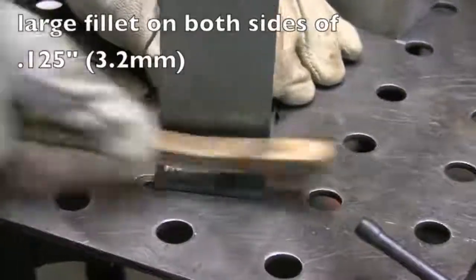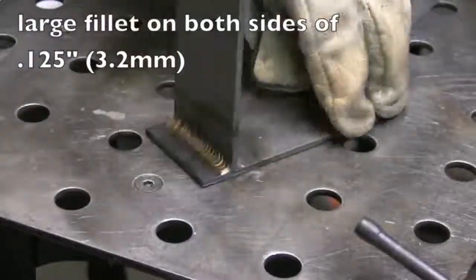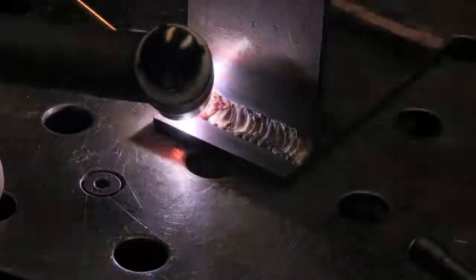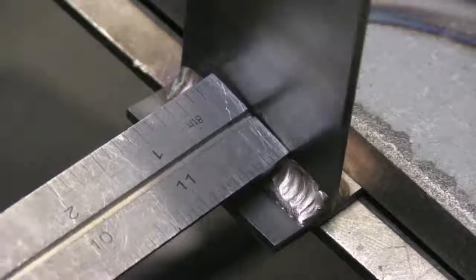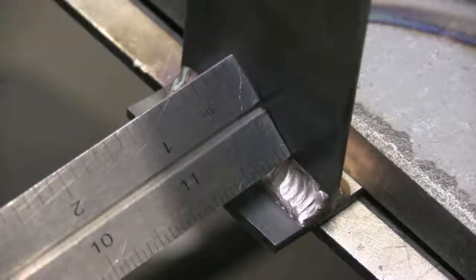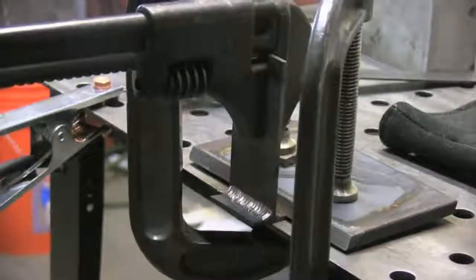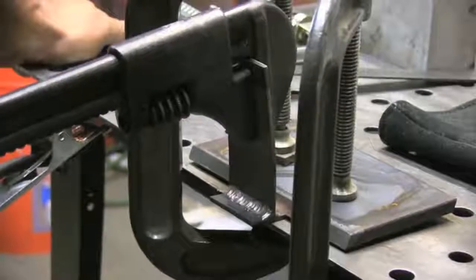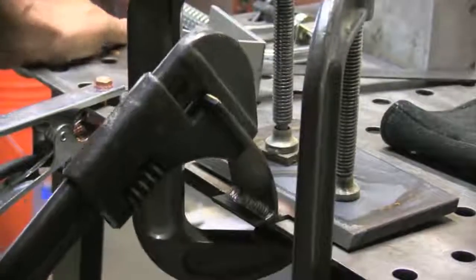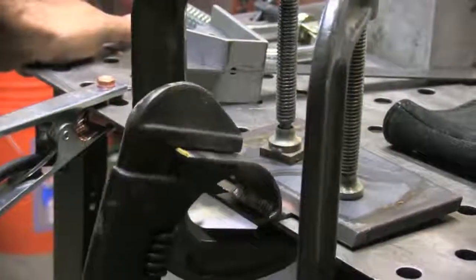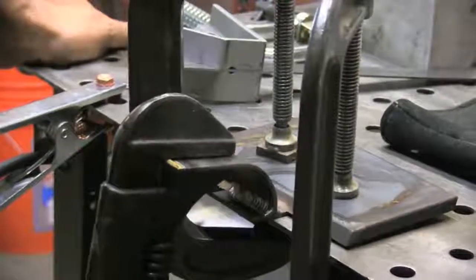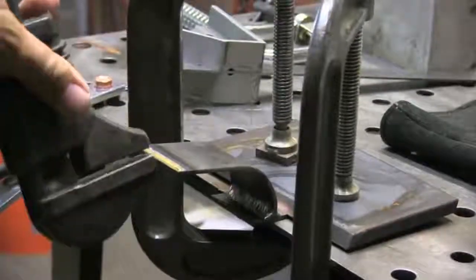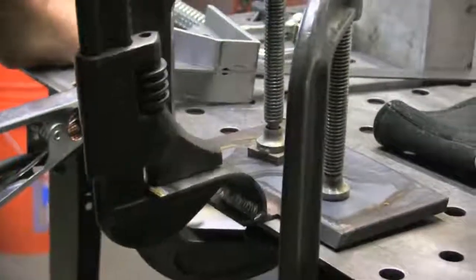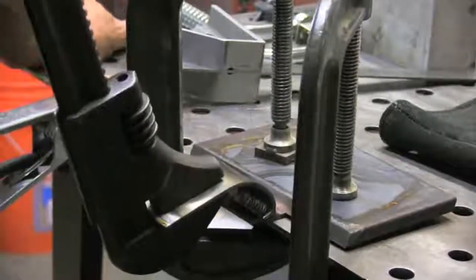Or even on that 1/8 inch thick, if I take one of those pieces and put extra metal, I weld it both sides and then put a big ugly fillet on one side, large leg size, that'll hold because it's done on both sides. So you have to compensate for the lack of strength and the lack of penetration of brazed metal. It needs to compensate with a much larger fillet if you want a decent strength joint.